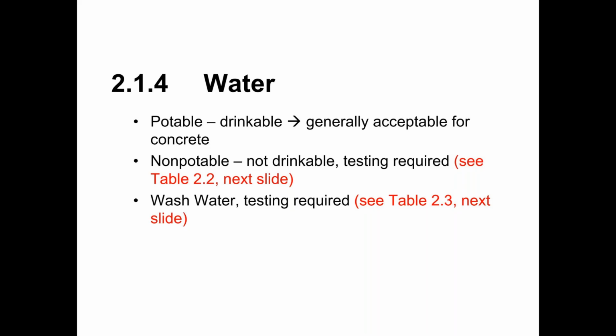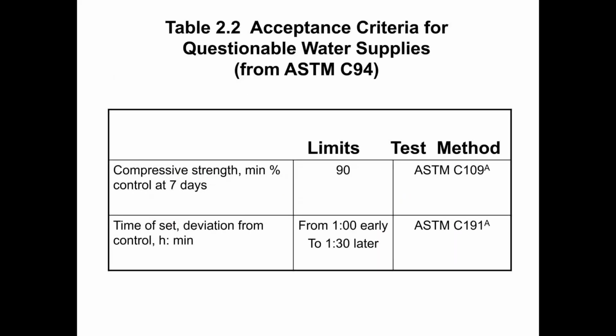If the water is non-potable or it's a questionable source, it's either not drinkable or we don't know if it's drinkable, then testing is required to determine whether or not it is acceptable for use in concrete. So the first round of tests that we should do are shown in table 2.2. So these are a couple of different tests. We should make samples using a known good water source and samples using the questionable water source. And we should test our compressive strength at 7 days and the set time for the two concrete samples.